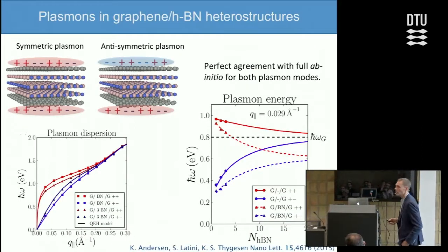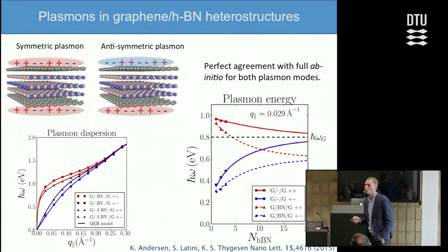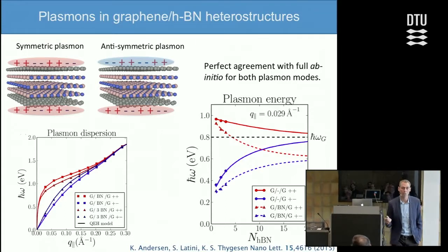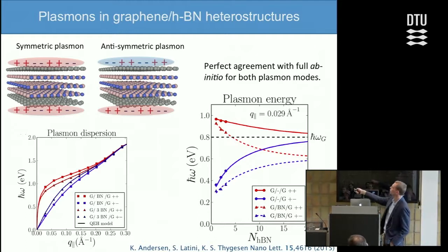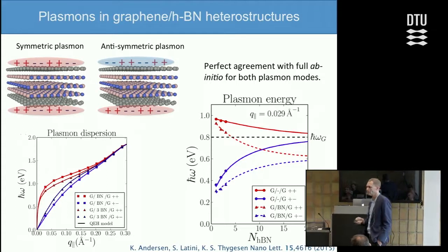So does it work? Yes. Here's an example where we computed the so-called plasmons in a heterostructure composed of two graphene layers with insulating hexagonal boron nitride in between. And what we find is two different types of plasmons.